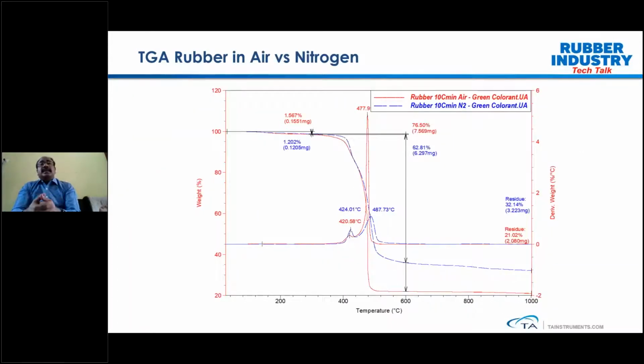Another aspect is the atmosphere we are using. As all of us know, the decomposition of any polymeric material, whether it's rubber polymer or thermoplastic, is basically a kinetic reaction, and that is purely dependent on the atmosphere we are using. In this case, we have taken the same rubber compound and tested it under air and under nitrogen. There is a clear change. The sample tested in air shows a faster decomposition compared to the nitrogen atmosphere. This graph clearly shows that even though the rubber chemistry is the same, the atmosphere has a major effect which totally changes the decomposition kinetics.